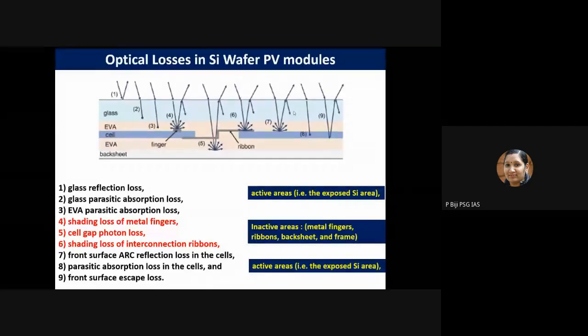But of course, these losses are coming from the active areas, which means the exposed silicon area. And the red highlighted ones, like the shading loss of metal fingers, the cell gap photon loss, and the shading loss from the interconnections and ribbons, these three losses are basically coming from the inactive areas, like metal fingers, ribbons, or backsheet, or the frame. So from that also the optical losses can happen. So that's the inactive area. Then further, the front surface ARC reflection loss, parasitic absorption loss in the cells, and front surface escape loss. So that's the active area again, related to your solar cell, which we have already discussed earlier.